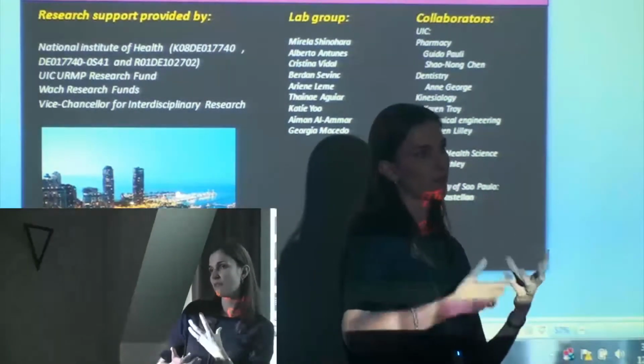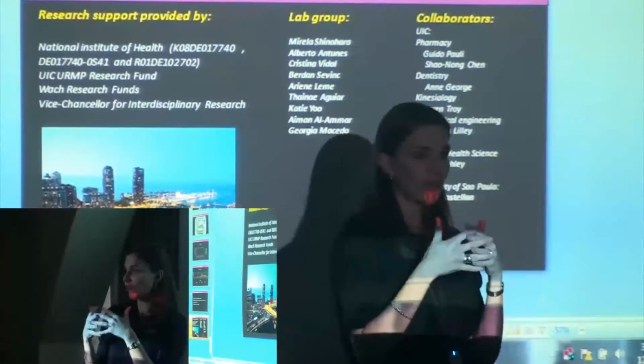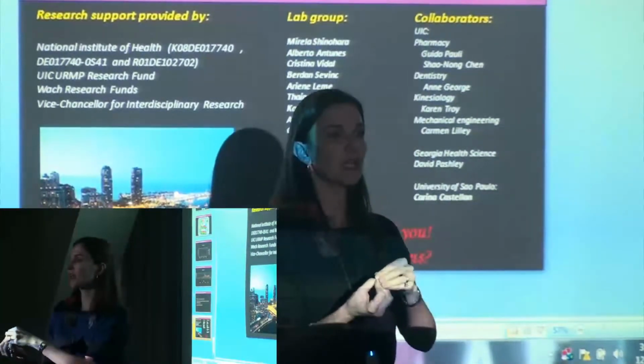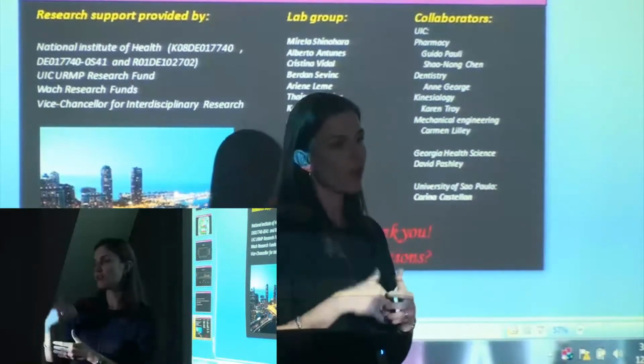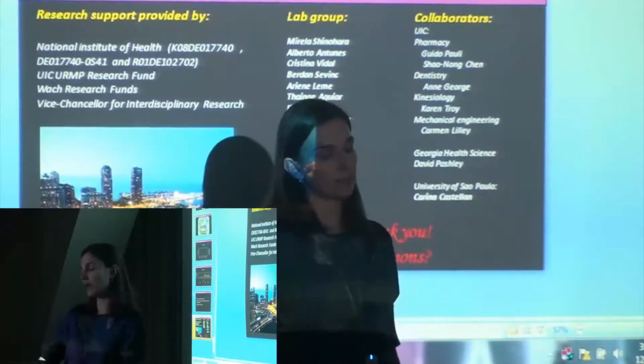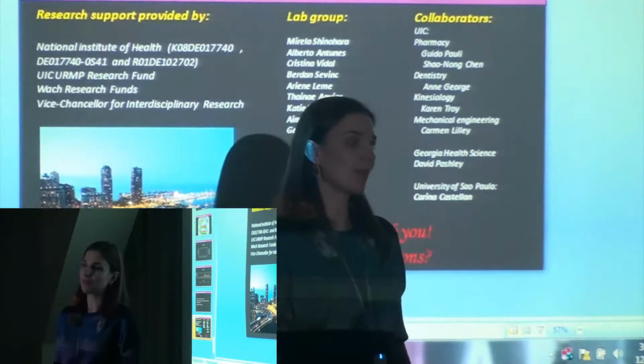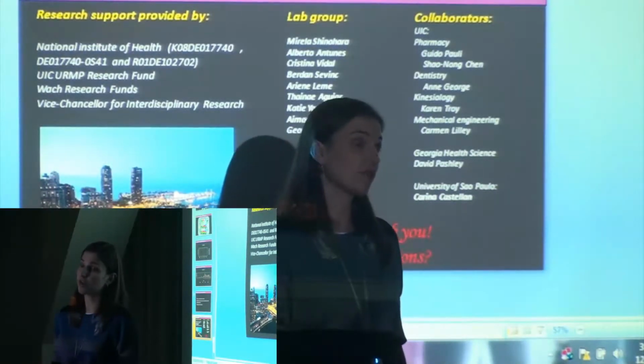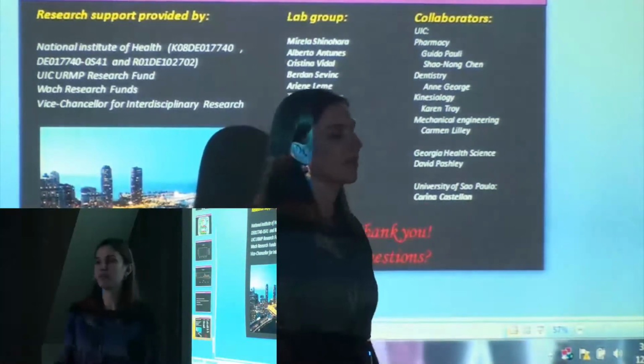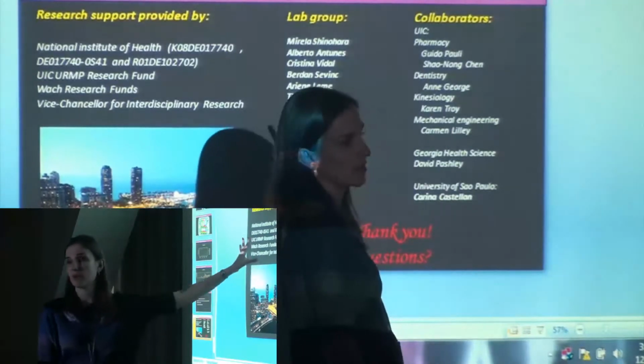So they are calcium binding, and in the saliva you have the calcium and the phosphate. When you have enough of both, you first need the calcium for nucleation and then the phosphate that's in the environment starts creating these amorphous calcium phosphates that will later on turn into crystals. But we have not gotten that far in showing that you actually have hydroxyapatite crystals. So right now, it's just based on hardness values that we get over the surface, or some of the microscopy that we did, confocal.